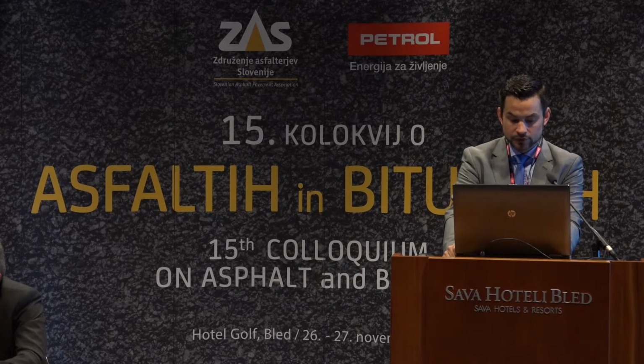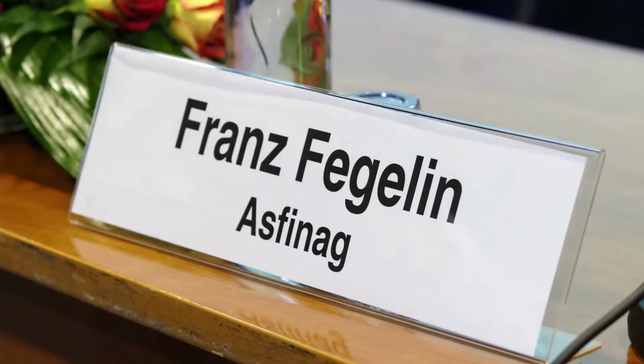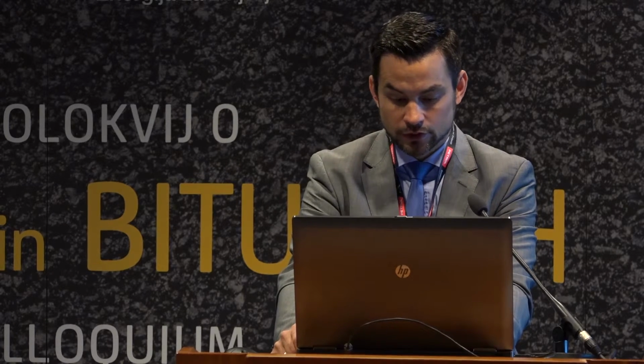The results of this test show us that for the high temperature behavior there are no new findings. The result of the low temperature test shows clearly that one of the important characteristics, the failure temperature of minus 25 degrees Celsius, was reached in any case. Material with reclaimed asphalt was a little bit better than asphalt mix made with traditional aggregates.